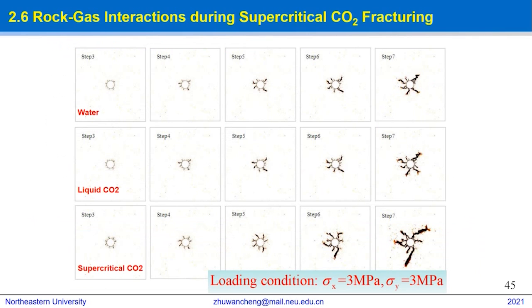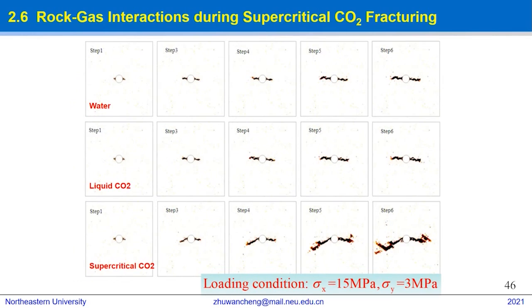mobility. The figure displays the evolving fracture patterns induced by supercritical carbon dioxide, liquid carbon dioxide, and water respectively. Comparing the fracture patterns induced by the three kinds of fluids, those induced by supercritical carbon dioxide are the most complex, followed by those induced by liquid carbon dioxide, and then water. These results show that the fractures are mainly initiated along the direction of major principal stress.